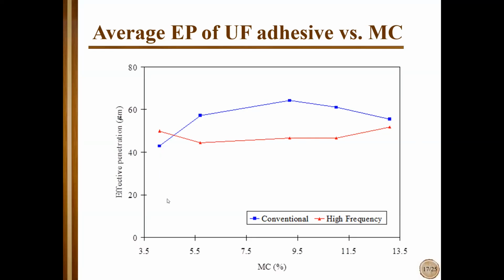The smallest was at the lowest moisture content, and then we reach maximum at, let's say, medium moisture content, about 9 or 10%. The main reason for this behavior is that very dry wood will absorb water from the adhesive bond quite quickly. So adhesive will lose mobility when water goes out, and so penetration is not so deep. If you have enough moisture content in wood, but not too much, then penetration will be, let's say, maximal.